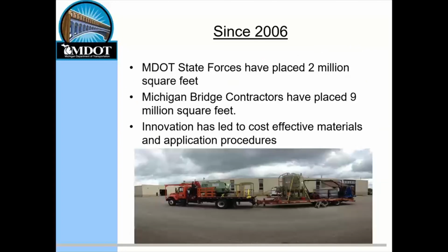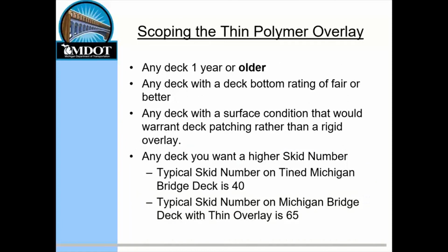Since 2006, our state forces have applied roughly 2 million square feet of thin epoxy overlay, and our Michigan bridge contractors have placed roughly 9 million square feet of thin epoxy overlay on our bridge decks. We've had several innovations over the years, and we've got a really good, tight spec and scoping process that we use. For scoping thin epoxy overlays in Michigan, we pretty much look at any bridge deck that's 1 year or older. We like to see our new bridge decks go through at least one season, one cycle of weather, to see how they're holding up before we cover up the surface.